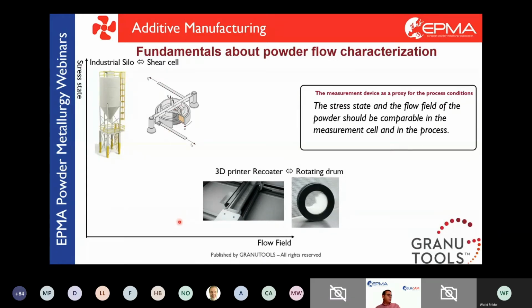Now, what we will focus on today is spreadability, and spreadability is done with a 3D printer recoater. And in the case of a 3D printer recoater, you need high flow fields because the goal is to recoat as fast as possible. The faster you recoat, the faster the piece will be printed, and you need almost no stress state because the powder is at atmospheric pressure or even lower depending on the process. So the goal is to find an instrument that will mimic those process conditions. And in our instrument at Granutools, we are using the GranuDrum. So it's a rotating drum principle to do this kind of measurement. So I will just spend a few minutes explaining what we are actually measuring with a rotating drum principle.